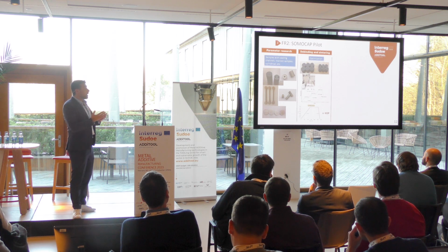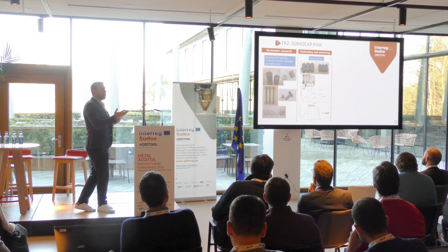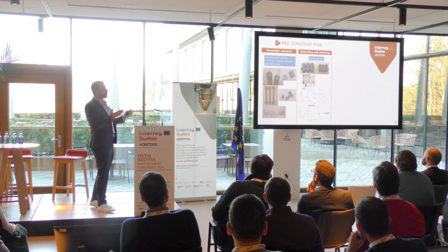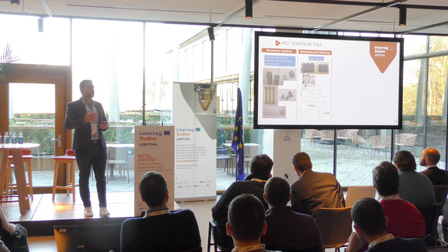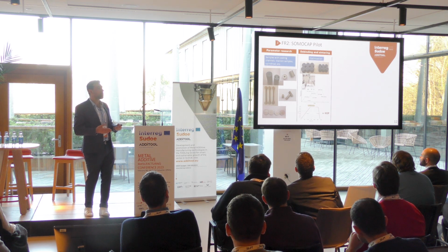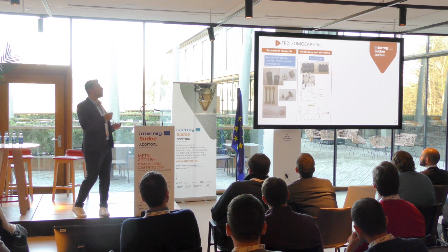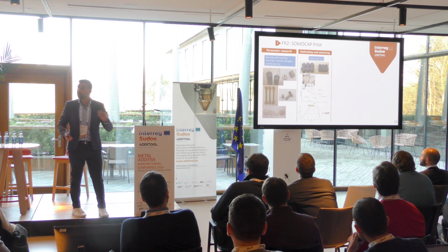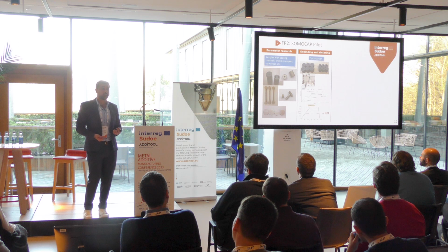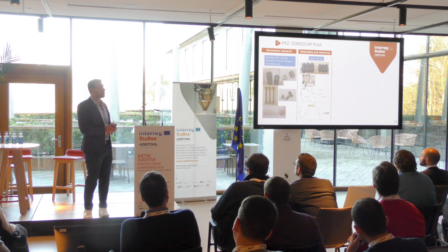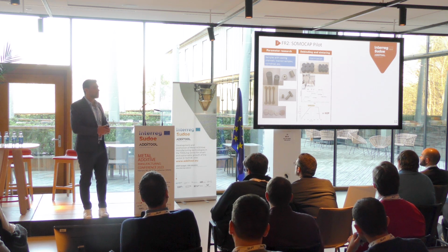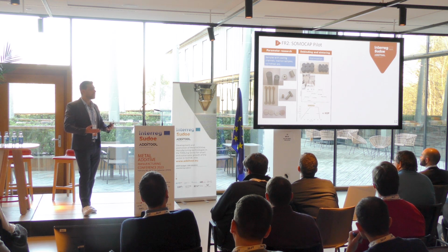For example, the first curve from the supplier is about 91 hours for debinding and sintering a part. So you have to launch the part on Monday, and you can take it out of the oven the next Friday. So it's not industrial, 91 hours.